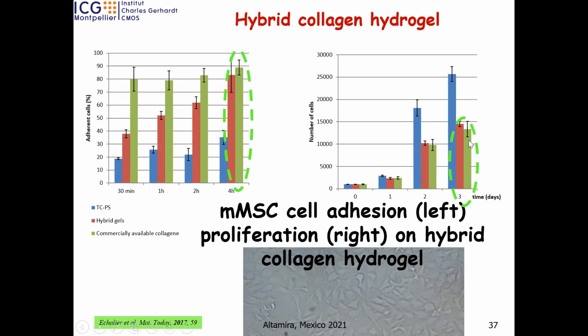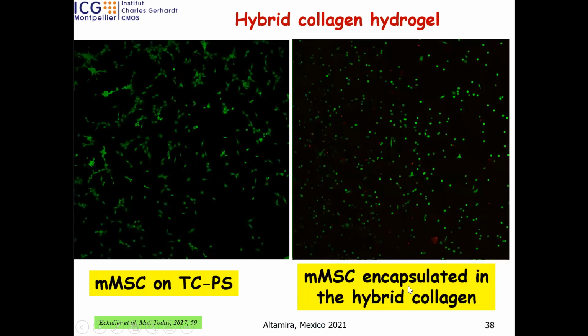It's very comparable. And you can see clearly here the cells are very well on the surface after 24 hours. Here, just to have the image, is fluorescence microscopy. Here you have the blank and our hybrid hydrogel. You can see clearly it's very similar, and sometimes you have some dead cells. It's expected because when you synthesize, sometimes you have maybe traces of solvent and so on, so there may be some contamination from your starting materials.